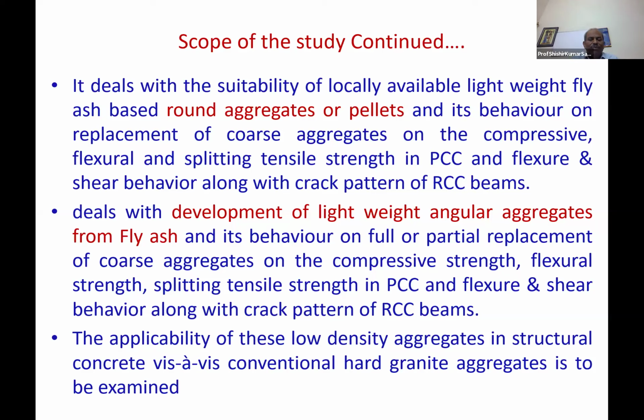This deals with development of lightweight angular aggregates from fly ash and its behavior on full and partial replacement of coarse aggregates on the compressive strength, splitting tensile strength in PCC and flexural behavior along with crack pattern of RCC beams. The applicability of these low density, lightweight aggregates in structural concrete, besides conventional hard granite aggregate, is to be examined. Besides strength, this weight is less. That is why the self weight of the structures becomes less. That way it is more advantageous.